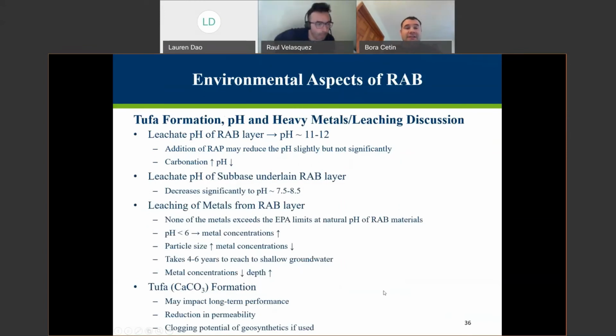So what are the environmental aspects of recycled aggregate bases? It wasn't part of this study, but we wanted to touch base on this. We have quite a bit of experience with this and wanted to summarize the last 10 years of studies that we've done on this topic. So the leachate pH of the RAB layer ranges from pH 11 to 12. And some of our studies show that addition of RAP may reduce this pH slightly, but not significantly, or mixing this RCA with the regular, conventional aggregates decreases that value a little bit, but not significantly.